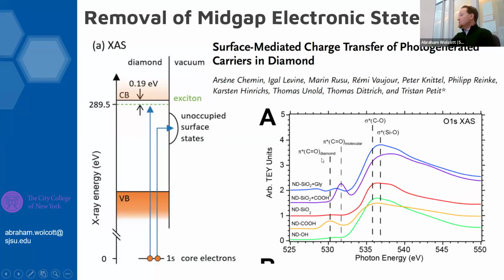And then we can do some chemistry and put those carboxylic acids back on by using silane chemistry. And then we can use that for conjugation protocols and everything else that we need to do if we want to have targeted biolabeling. But I really want folks to look at the contrast between the green, orange, and red data sets. The main idea is that this peak in this area is directly correlated to our unoccupied surface states that we see in the diagram on the left-hand side.